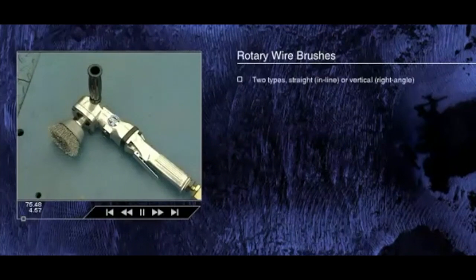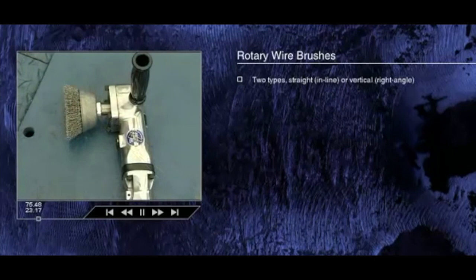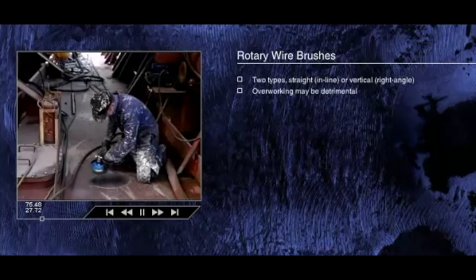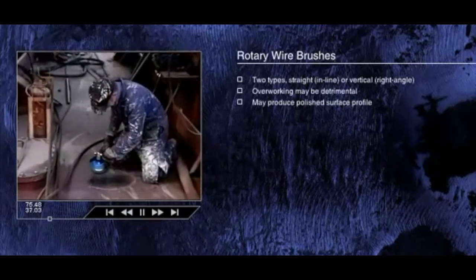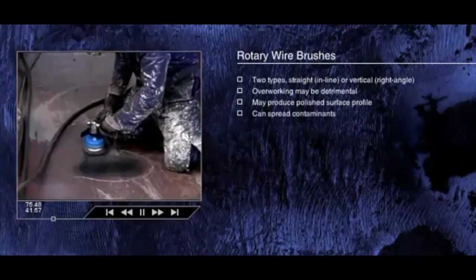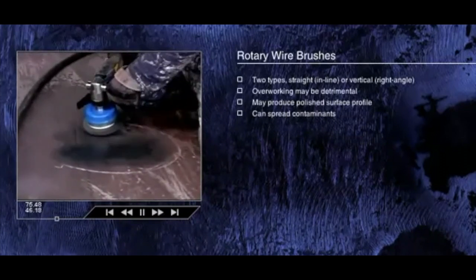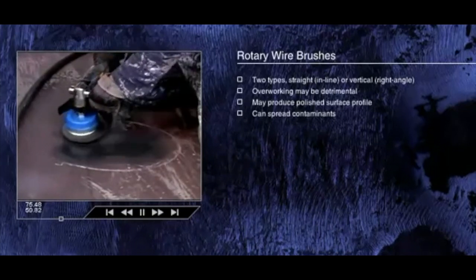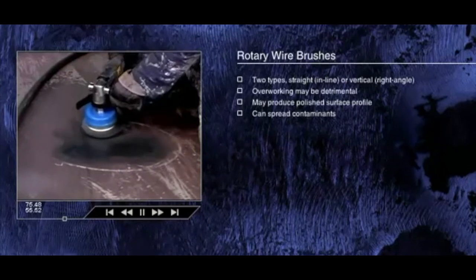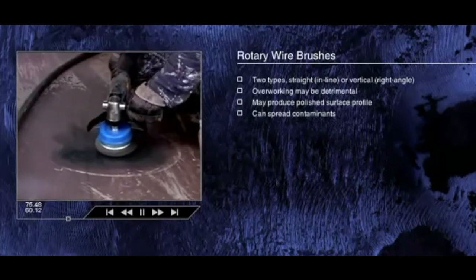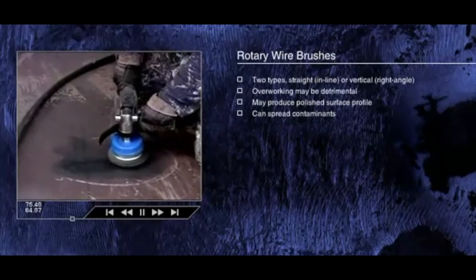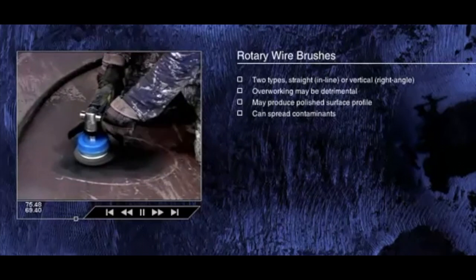The machine design is of two general types: straight or in-line, or vertical or right angle. Shown here is a right angle wire brush. Overworking the surface with a wire brush may be detrimental because excessive burnishing develops a polished surface which provides a poor anchor for most coatings. Rotary power wire brushes can also easily spread oil and grease over the surface. Therefore, solvent cleaning is an essential step before power wire brushing. Problems with polishing the surface rather than providing a roughened surface are particularly likely with this technique, and mean that the use of rotary wire brushes is considered to be less desirable than other forms of power tool cleaning.